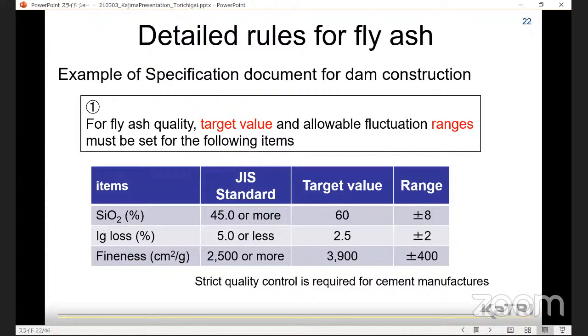Here, we introduce an example of the detailed rules for using fly ash in dam concrete in Japan. This slide shows an example of a dam construction specification document that is used at my work site, Gokayama Dam. 1. For fly ash quality, target values and fluctuation ranges must be set for the following items, like SiO2, ignition loss and fineness. This is the target value of the JIS standard. And at our site, the target values and the ranges are decided as you see.